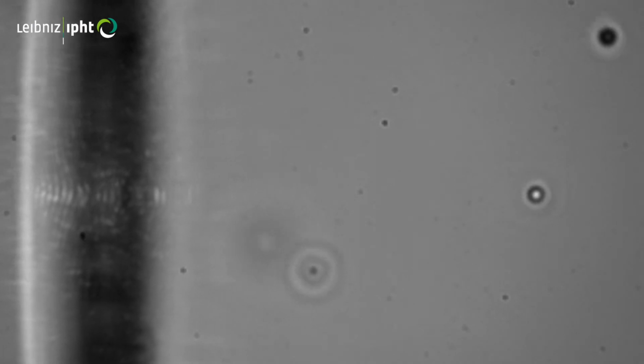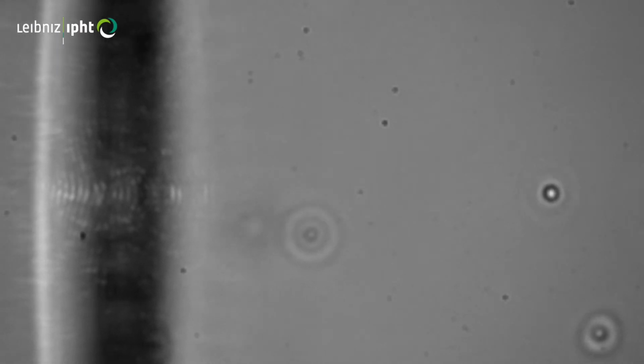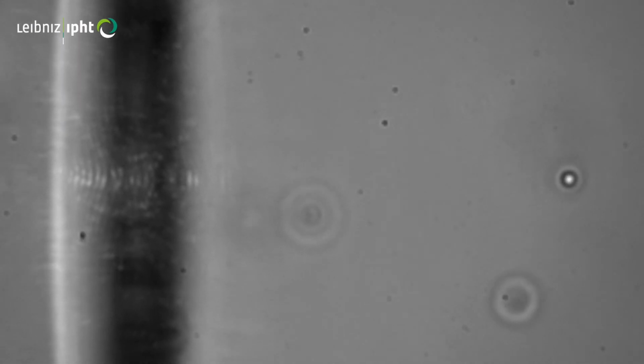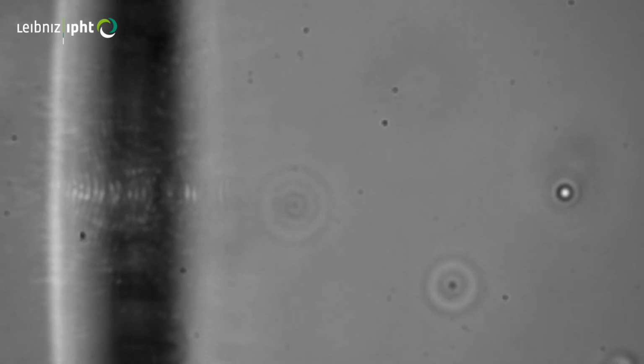The ultra-high numerical aperture of the metalens printed on the optical fiber, which we call a metafiber, in combination allows us to trap just one single particle in the focus. The focus is approximately 50 micrometers in front of the facet. The focus is so small that once a second particle enters the focus, the first particle that was in there is immediately kicked out. We demonstrate the optical trapping by moving the fiber left and right and up and down, to show that the particle is trapped in a non-contact mode.